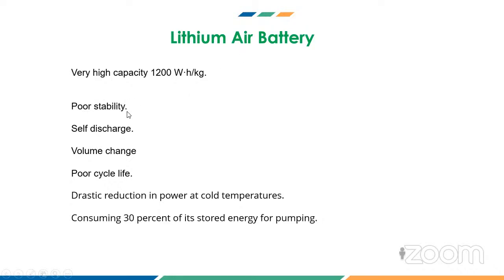Some of the drawbacks of this lithium air battery: it has poor stability. Poor stability means life is less, and any abuse, that means over discharge or overcharging, may lead to explosion. That is one of the biggest problems of this battery. And self discharge is another issue. Volume change, poor cycle life. Life is less. That means periodically we have to replace the battery. And drastic reduction in power at cold temperature. That means it is not suitable for low temperature conditions.